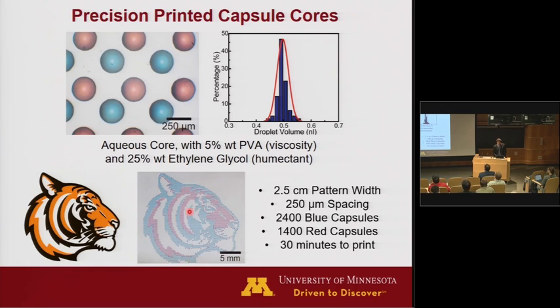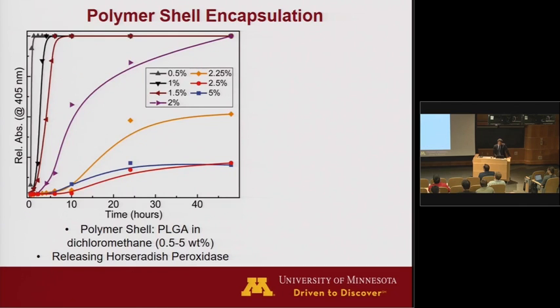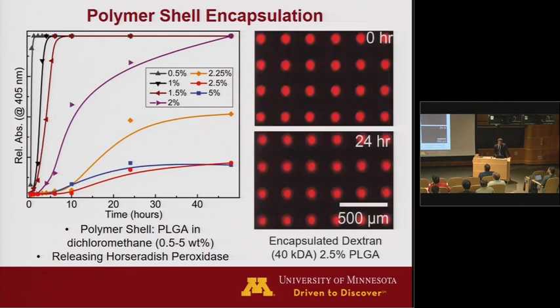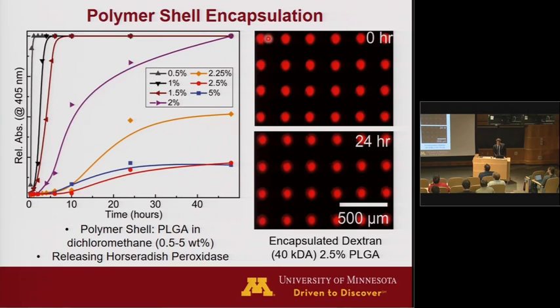So this is a complex drawing of a tiger here of two types of cores that are being printed in this multiplex manner. So what we do here is that we then encapsulate these cores with a PLGA shell, which retains the contents of the core. And we can even immerse, depending on what the core is, in this case it's a dextran, you can immerse these underwater for 24 hours and the contents of the core don't release within this limited time period. Although over a long time period you will get diffusion through the shell, you can control the concentration of the shell to limit your diffusion.